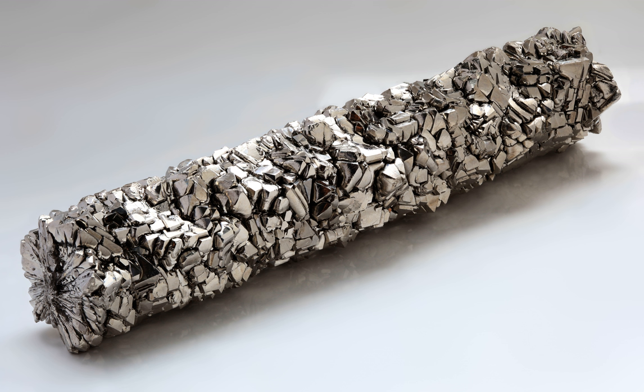The currently known processes for extracting titanium from its various ores are laborious and costly. It is not possible to reduce the ore by heating with carbon, as in iron smelting, because titanium combines with the carbon to produce titanium carbide. Pure metallic titanium, 99.9%, was first prepared in 1910 by Matthew A. Hunter at Rensselaer Polytechnic Institute by heating titanium 4 chloride with sodium at 700 to 800 degrees Celsius under great pressure in a batch process known as the Hunter process.